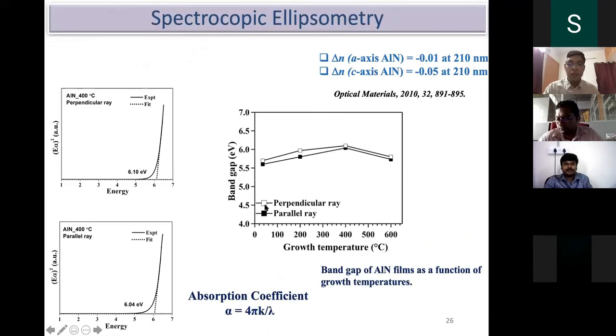Well, we have calculated the band gap also. With temperature, you can engineer the band gap. It is simple aluminum nitride. And when you compare them, the birefringence from this technique, C-axis and A-axis, you can get a close by result, but there is a change in the case of A-axis oriented aluminum nitride, which I will discuss further.